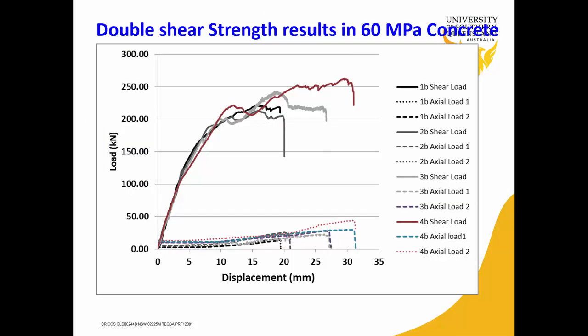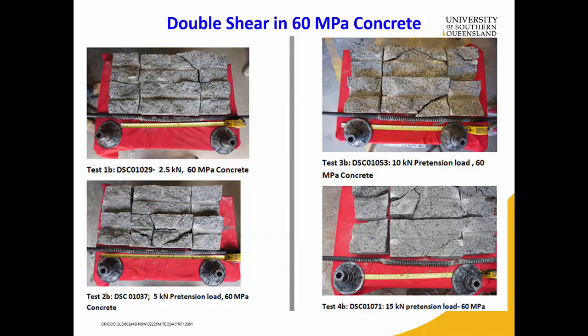Double shear tests were also carried out in 60 megapascal concrete block, and you can see the same type of data here. The vertical axis shows load in kilonewton and the horizontal axis shows displacement in millimeter. Data below belong to the axial load variation, and on top is the shear load variation. We can see the shear strength varies from 20 to 27 ton depending on the value of pretension, bearing in mind that the value should be divided by 2 to come up with the shear strength of the system.